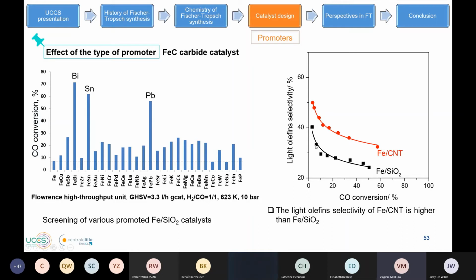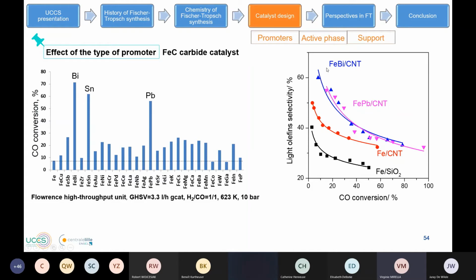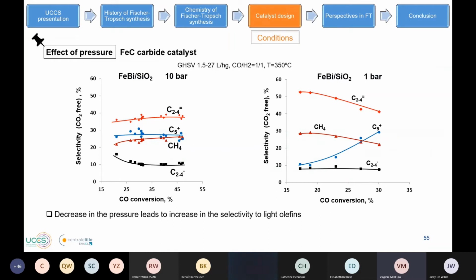And also when we use another support, the carbon nanotube support, we observe exactly the same tendency with iron. And when we promote the iron with bismuth or lead, we observe an increase in the selectivity of olefin, but still the same tendency: even with the addition of the promoter, the selectivity decreases when we increase the CO conversion. We study also the effect of the pressure, and we observe that when we decrease the pressure on the bismuth catalyst, the selectivity is also improved.